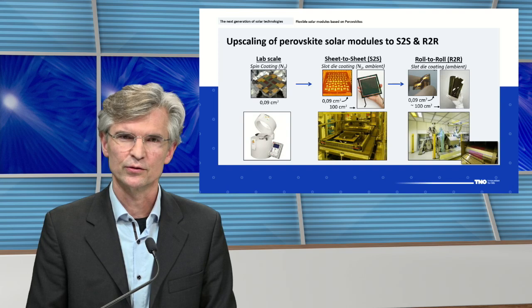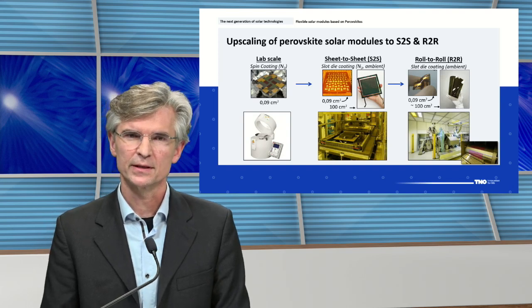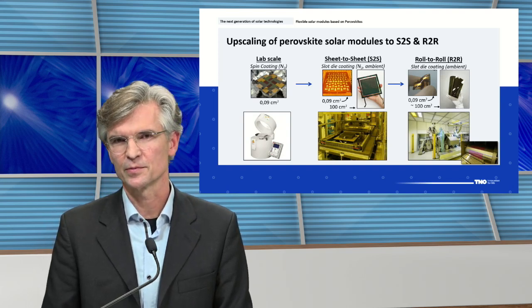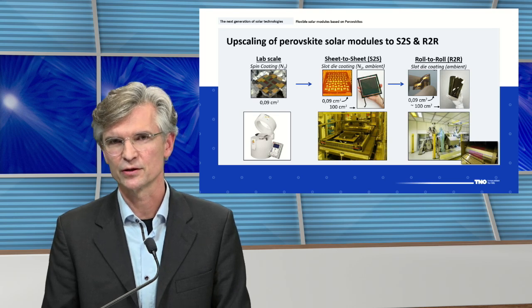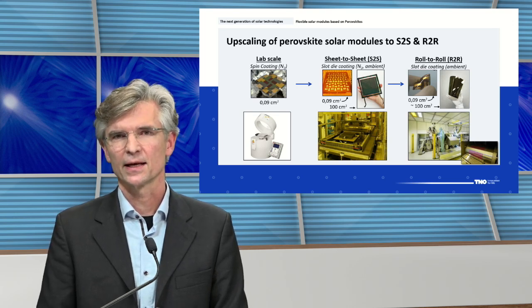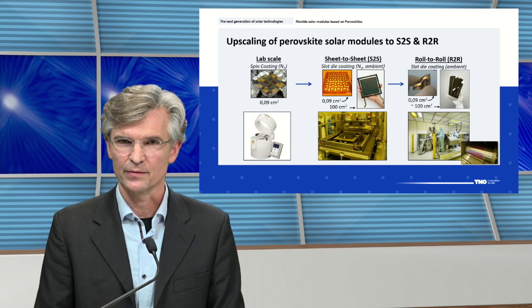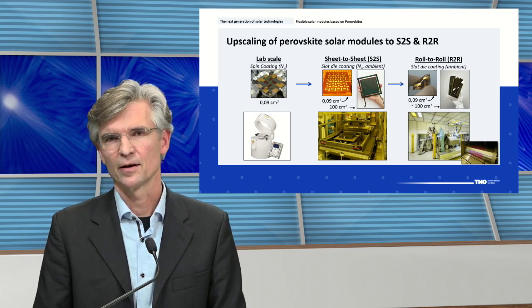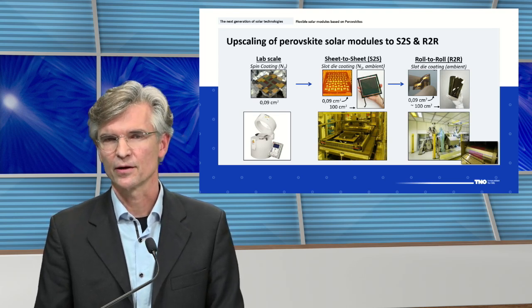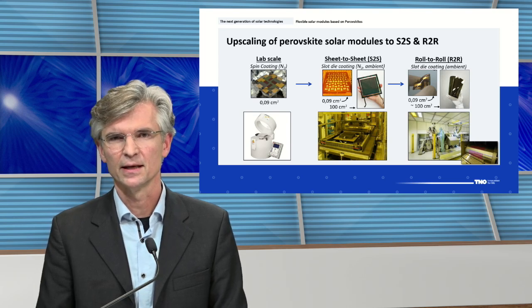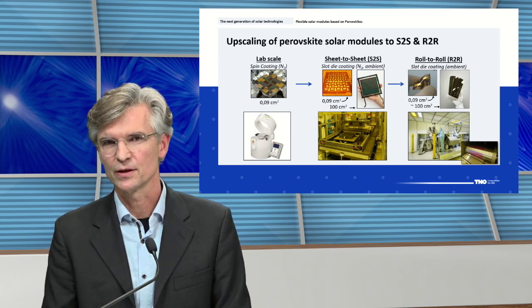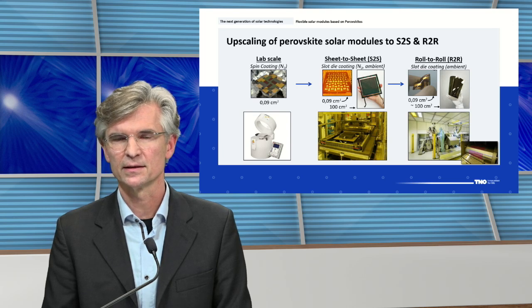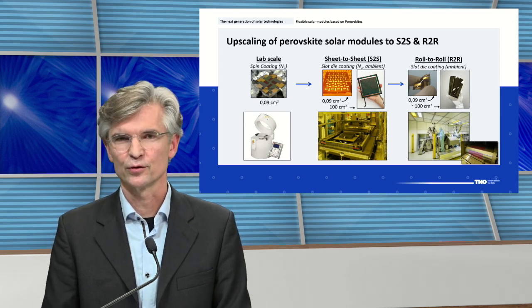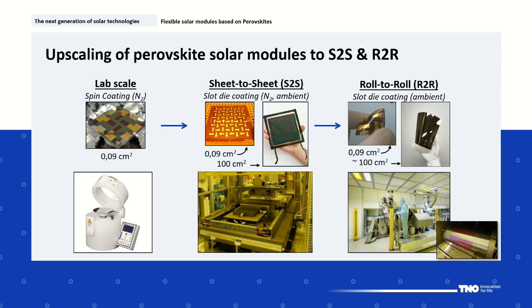If we then move towards sheet-to-sheet processing, we make a similar device structure, but then on a substrate that is much larger. It's about 6 inch. And then we can make the same type of devices, but we can also make mini modules with an active area of 10 by 10 square centimeter. And to make these devices, we use scalable techniques, like slot die coating as indicated in the picture below.